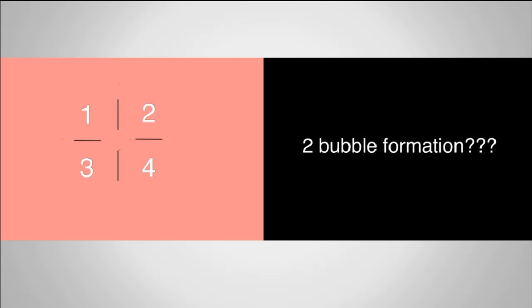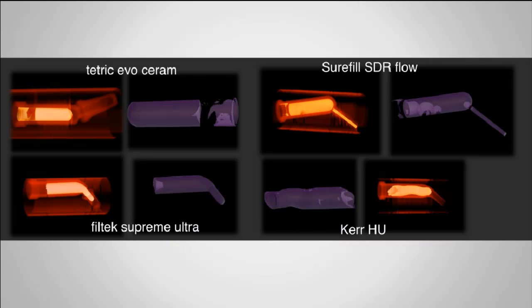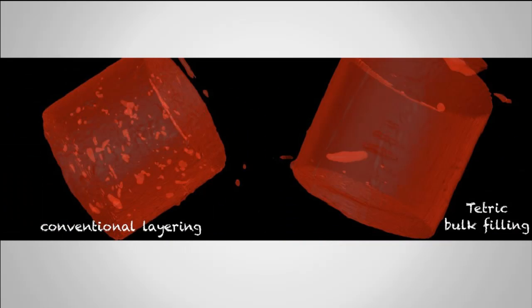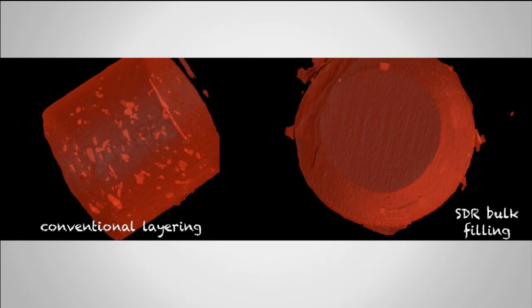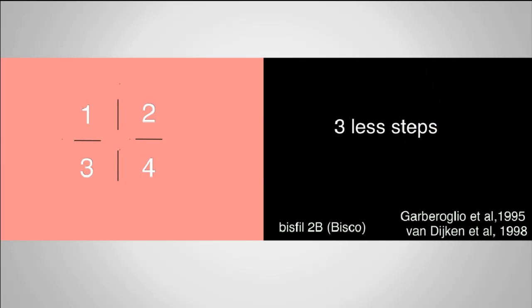The second idea about using bulk fill composite is that when I do too many layers, usually inside the composite, I begin to increase the number of failures, like bubbles and voids. This is something that I don't see, but if I check in the X-ray, this is something that I notice. If you put too many layers, you begin to increase the number of voids and failures. And I think that using bulk fill composites, this is something that you will also avoid. This is the second advantage of bulk fill.